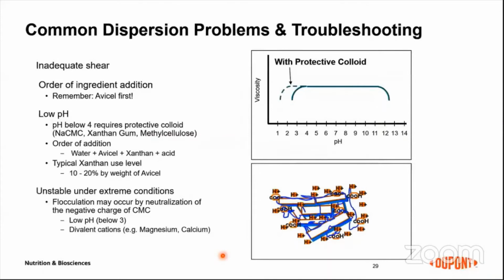So flocculation may occur by neutralization of the negative charge of CMC polymer. Any low pH, like below 3, or divalent cations, even magnesium or calcium ions, might have an impact on the colloidal MCC suspension stability. So in this case, we need to think about either increasing the colloidal MCC use level a little bit higher, or adding the protective colloid.